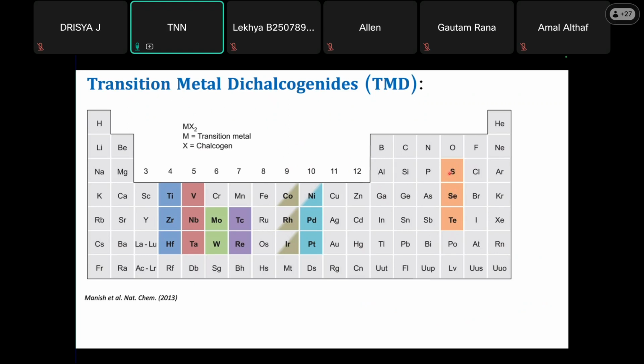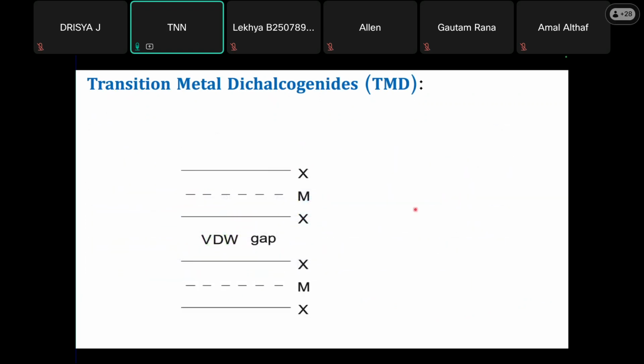These act like very nice semiconductors having a reasonable band gap, and they are also thermodynamically stable. Some of the chalcogens are layered, but others are non-layered. But most of these metals form nice layered structures with chalcogens like sulfur, selenium, and tellurium. They form in bulk, but with a van der Waals gap. The van der Waals gap is typically, as in graphite, around 3 angstrom, and it can go to 6 angstrom. Since there is a van der Waals gap, you can take one layer out of the other. One layer is actually a tri-layer system with two layers of chalcogen, where the middle layer is a metal.